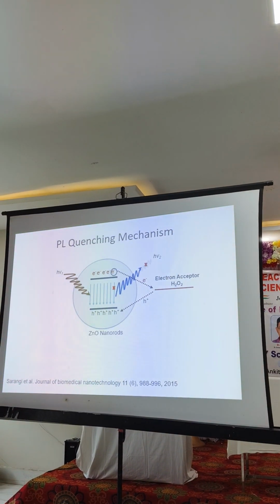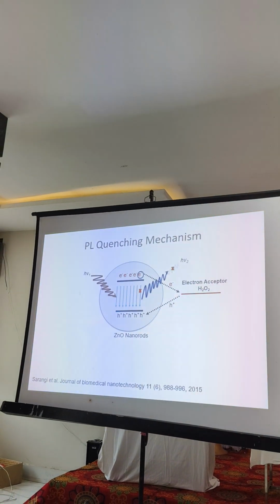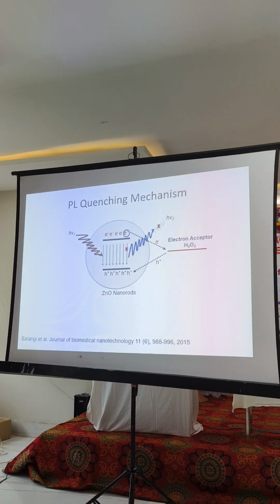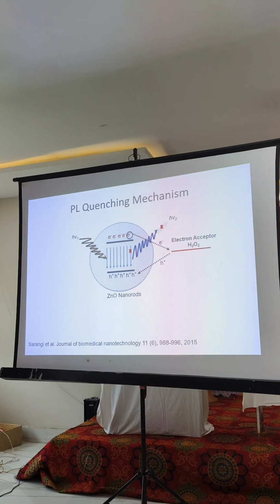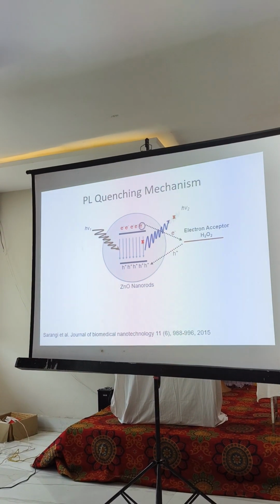And this hydrogen peroxide takes away this electron. So instead of luminescence, I won't get luminescence. I am supposed to get luminescence if I have a direct recombination. But in between I have a step, where this hydrogen peroxide takes out the electron. So the luminescence that I used to get, I don't get. Because of hydrogen peroxide, luminescence is lost, so I have less luminescence. The more hydrogen peroxide I have in the blood serum, the more the luminescence will decrease, and henceforth I know that amount corresponds to this much glucose. Understand? Clear? I believe you are.